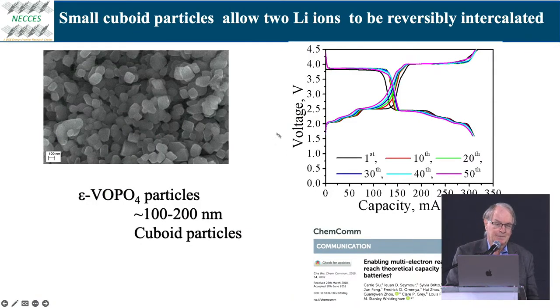So if we do that, then we get these little cuboids. They're about 100 to 200 nanometers. And I'm going over this unfairly fast to the graduate students who did the work. It took them about 2 years to learn how to make these cuboids. They're electrochemically active, so it's not all that easy. But here's the discharge plateau. Just what you expect. Vanadium 5 to vanadium 4 at about 4 volts. Vanadium 4 to vanadium 3 at about 2.5 volts. Our concern was, can you, in fact, put two lithium ions into a crystal lattice and not destroy that lattice? So if we look closely here, you'll see the black line is the first lithium insertion and removal. The purple one is the 50th, and the purple is, in fact, better than the first one.